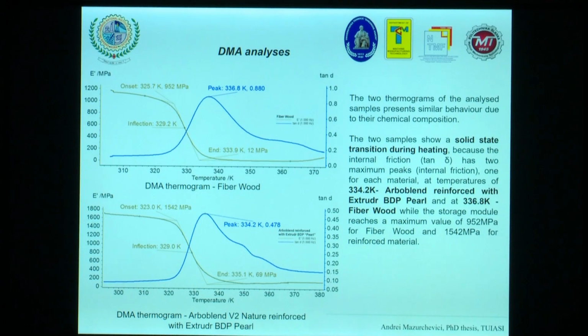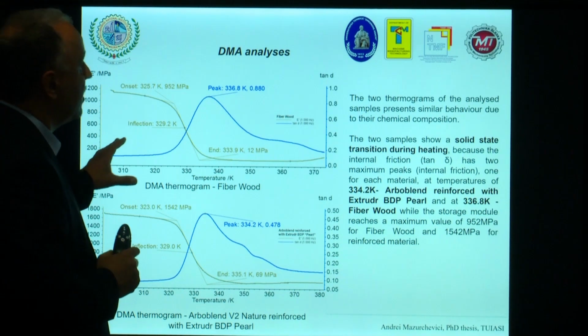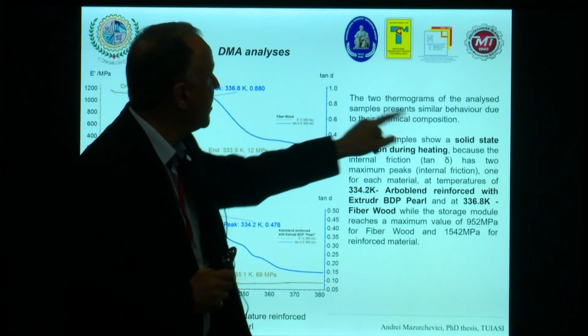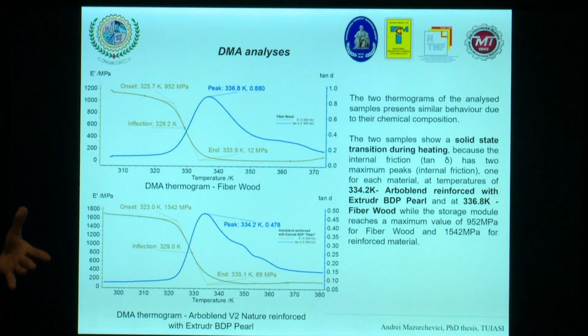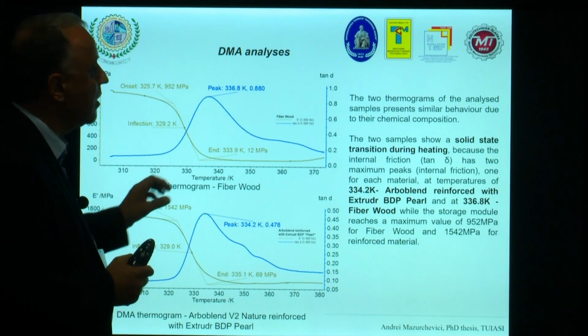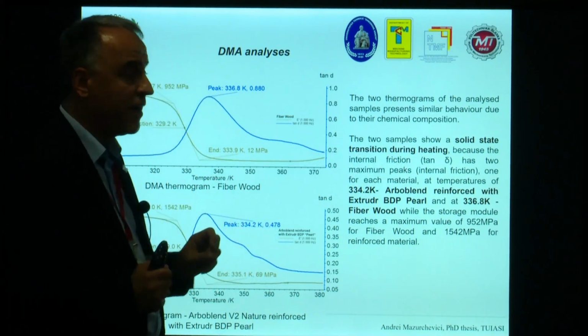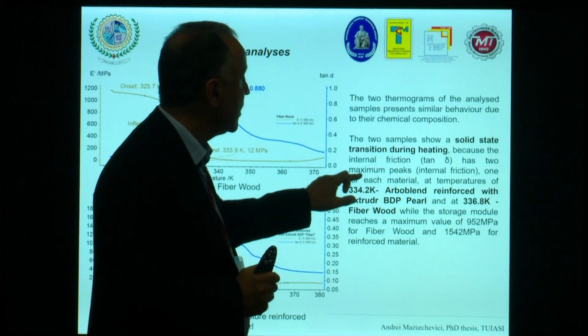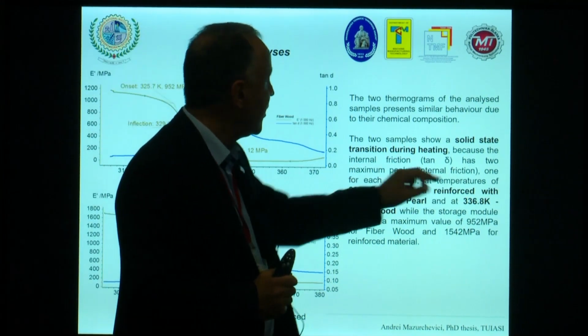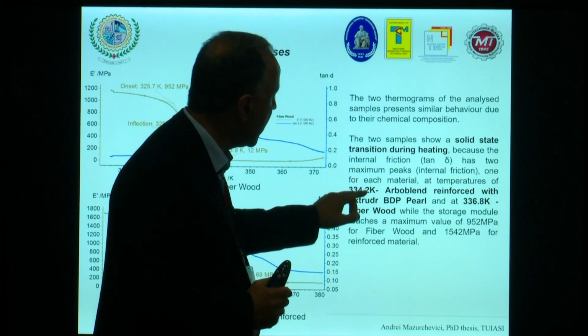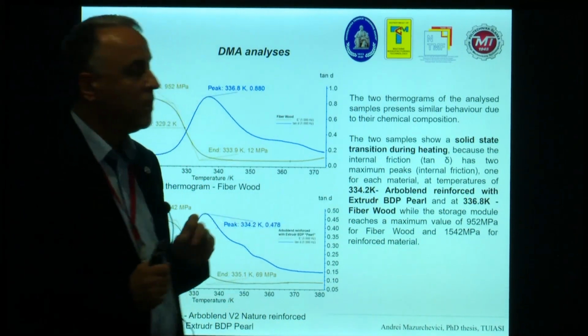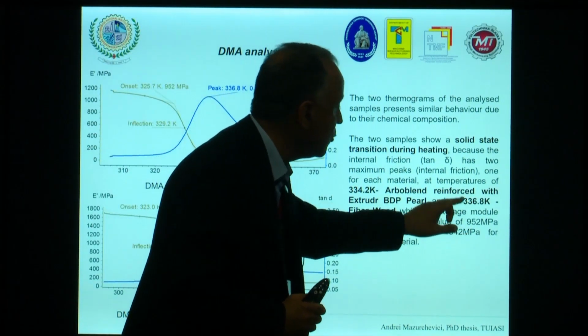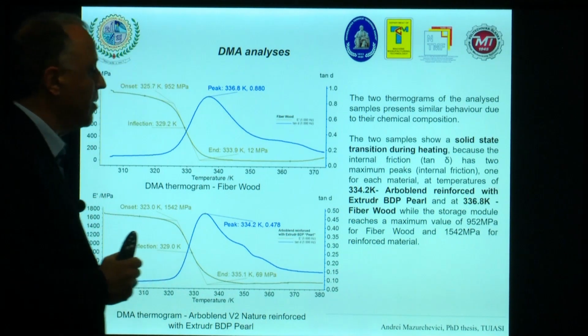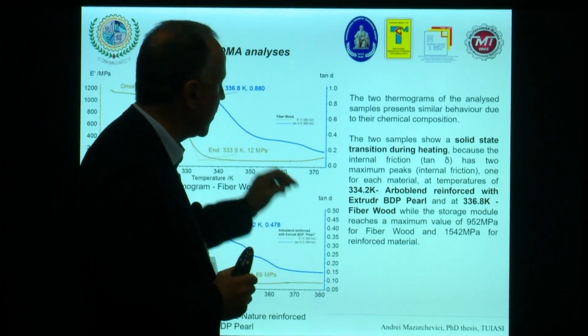And DMA analysis. I explain what DMA analysis means. We have two thermograms of an analyzed sample that present similar behavior due to the chemical composition. Biodegradable materials have more or less the same chemical composition. So the samples show a solid state transition during the heating. Why? Because the internal friction tan delta has two maximum peaks at the temperature of each material, around 334 in case of Arboblend reinforced with Extrudr BDP, and around 2 Kelvin degrees more in case of Fiber Wood.